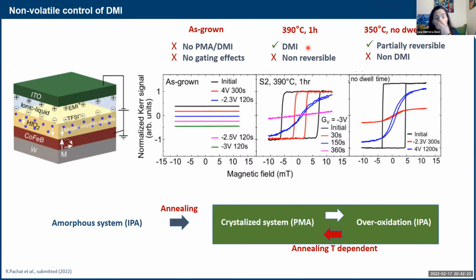And then at this point we said, well, maybe we can find a compromise. Let's try to anneal at a little bit lower temperatures, and let's see if we can find a point in between. So we annealed at 350, so not so well crystallized as 390, and we recovered some partial reversibility. There was PMA, but no DMI. So then I think what we learned from here is that